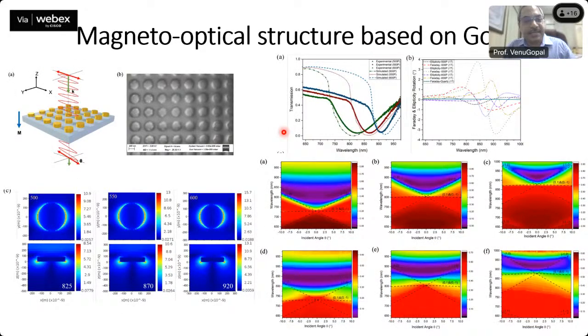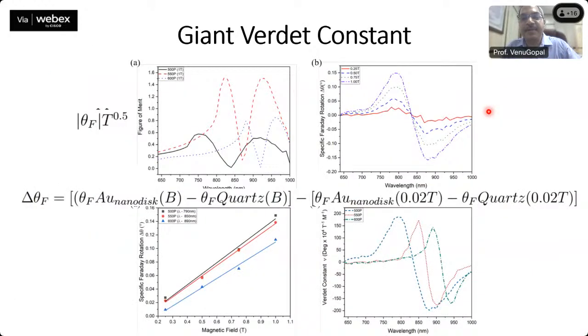Okay. So this is again the most recent one which we are writing up currently, and it is not just magnetic materials. Even if we take simple 2D grating structures which are made of metal discs, gold nano discs in this case, we see huge magneto-optical response from these structures. This is because of the magnetic Lorentz force getting enhanced because of the resonant mechanism which we are showing. The plasmon resonance and the lattice mode match in this case. And when this happens, we can have a Verdet constant which is as high as the highest Verdet constant reported in the literature.